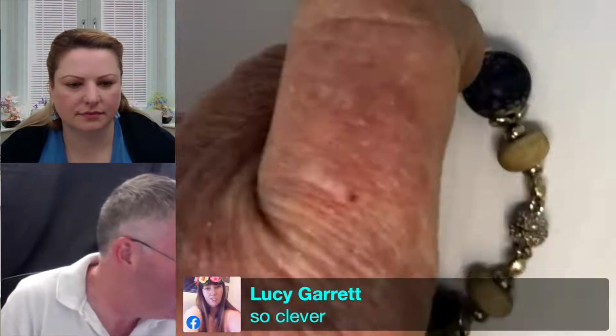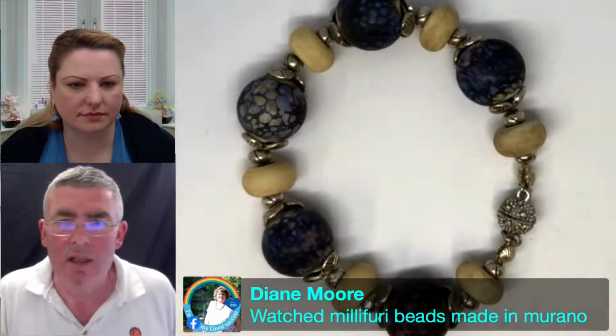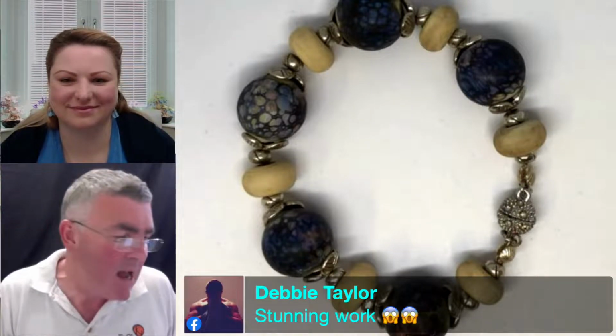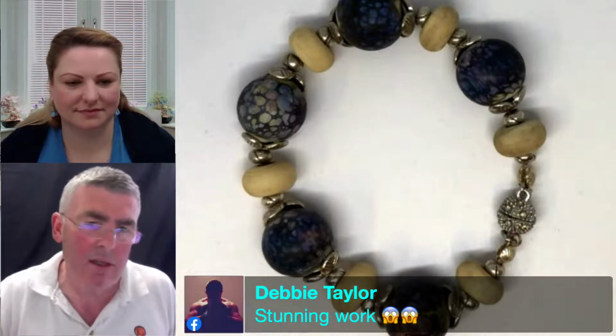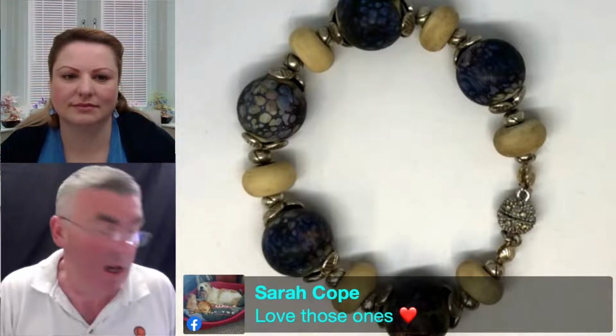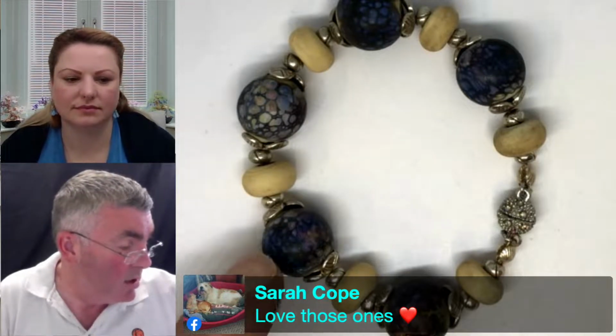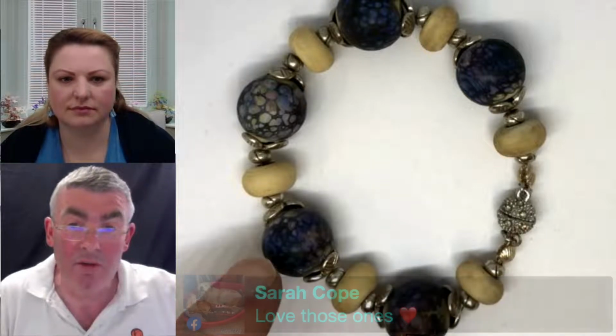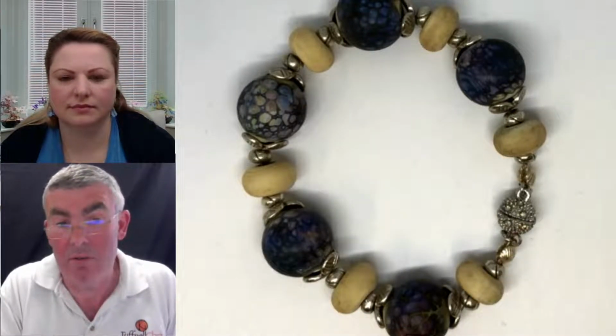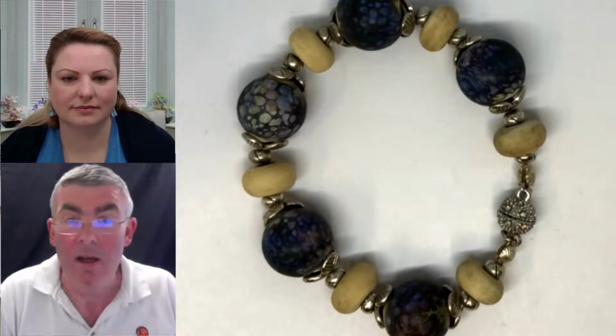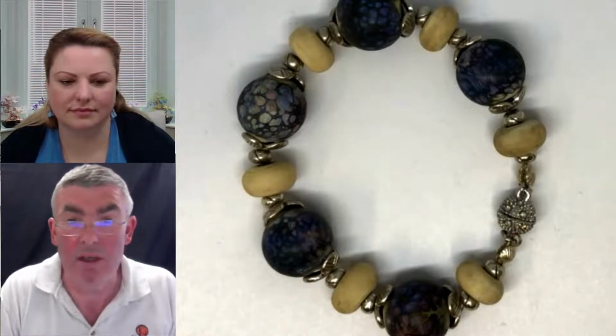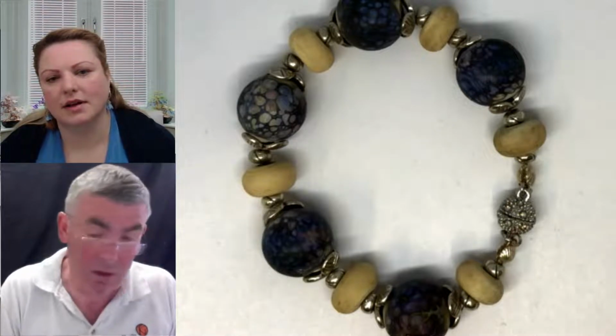These are a little bit different. These are quite matted, these ones. There's a technique where you can use a very mild acid, and you can matt the beads, so you can take the surface sheen off the beads, and it mutes them down. It makes them quite attractive on some colours. And this is actually only a frit bead. So the central ones, the darker ones, are just a dark glass coloured bead with a frit, which is the confetti that we talked about, the breadcrumb, and the bead is rolled through it. And then they've been dipped in this acid for about 3 minutes, and then neutralized, and then strung up.